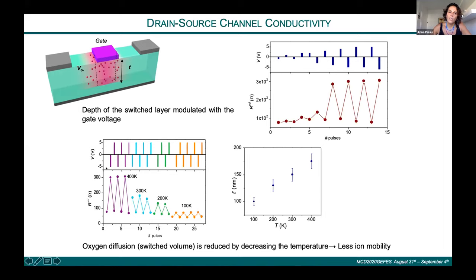If we perform the same experiment with exactly the same voltage pulses, positive and negative, at 400, 300, 200, and 100 K, we observe that this difference between the resistance is higher at higher temperature, because in this case, we have higher mobility of the oxygen. And at this temperature, it's much lower because the mobility is lower. And here we can see the evolution of this thickness as a function of the temperature.